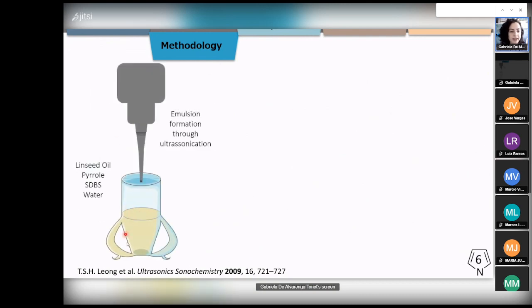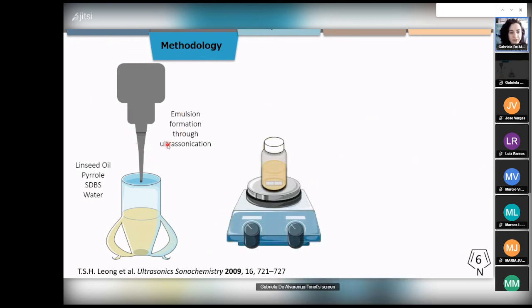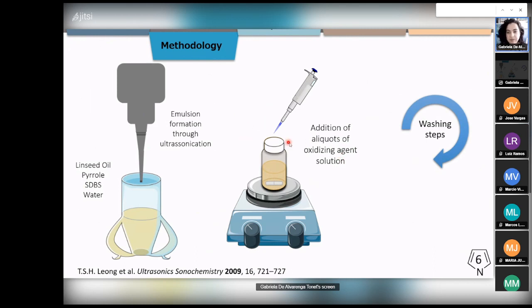So this is the main strategy, but experimentally, this is done by adding all the ingredients, linseed oil, the monomer, the surfactant, and water to a glassware. It's constructed especially for this synthesis. And we use an ultrasonicator to form a nanoemulsion, because this will offer enough energy for us to disperse the oil in droplets that are small enough to reach the nanoscale. Then we simply add them to a mixer, and with a slow stir, we add aliquots of the oxidizing agent solution, and this will form the capsules. Then we wash these capsules and go into the analysis, which is what I will be showing to you now.